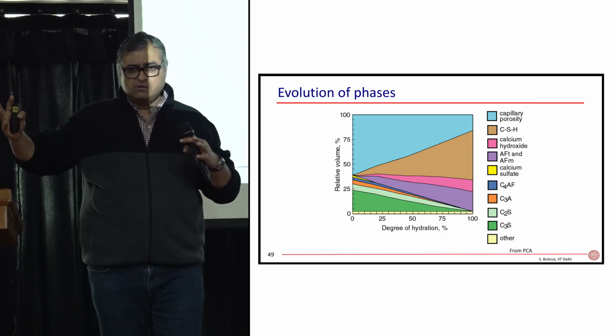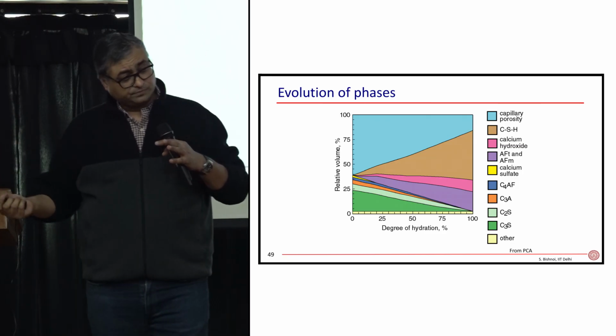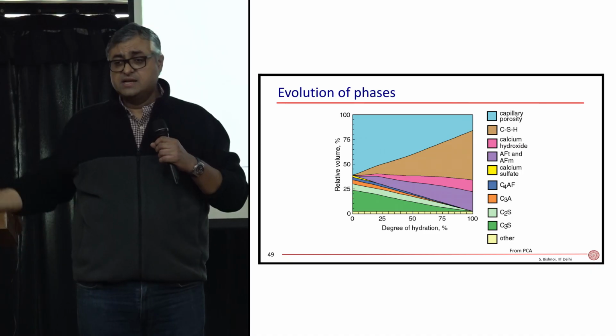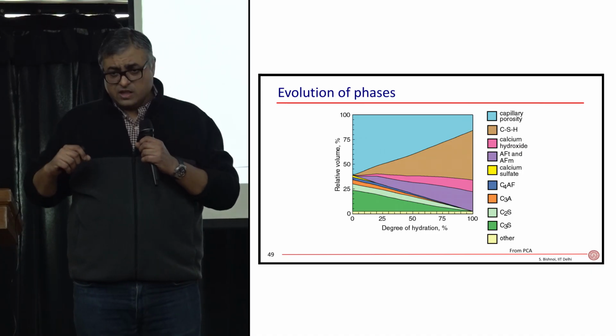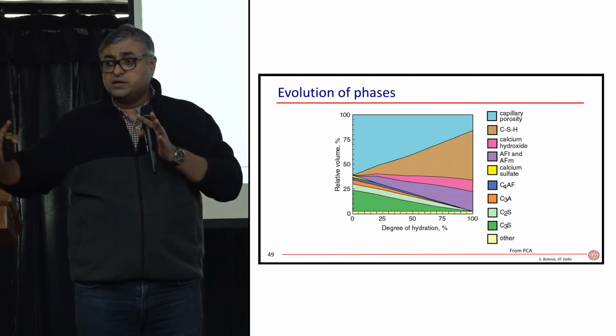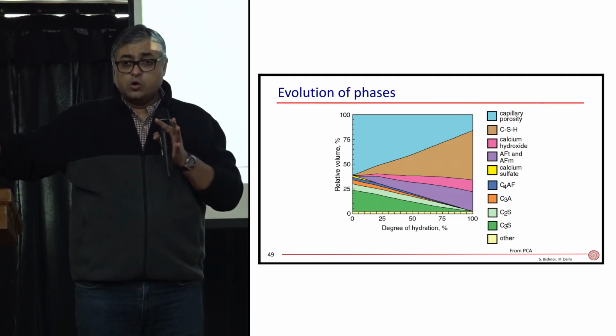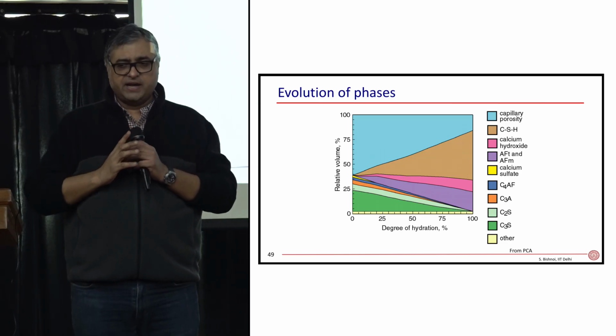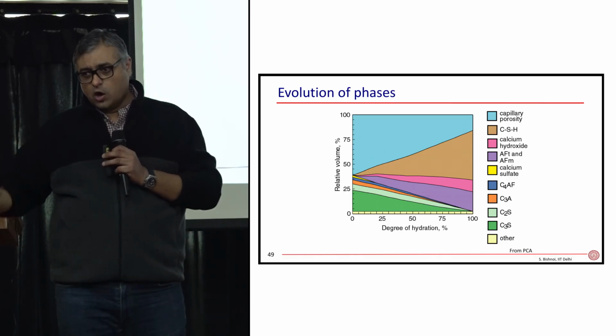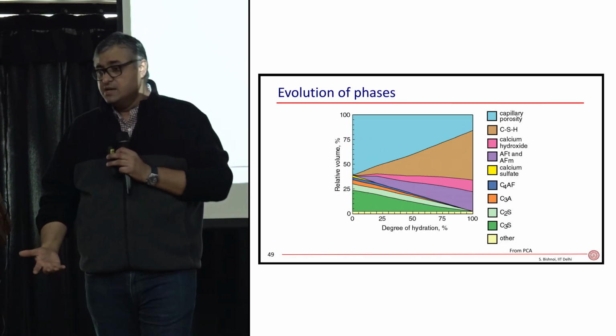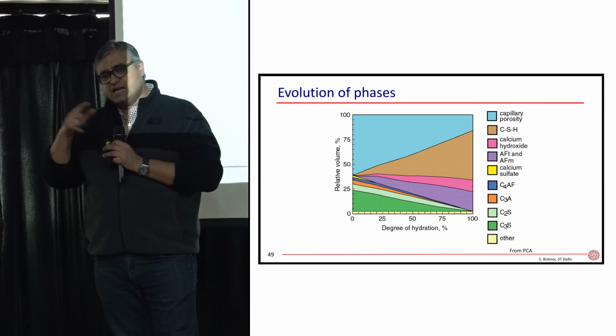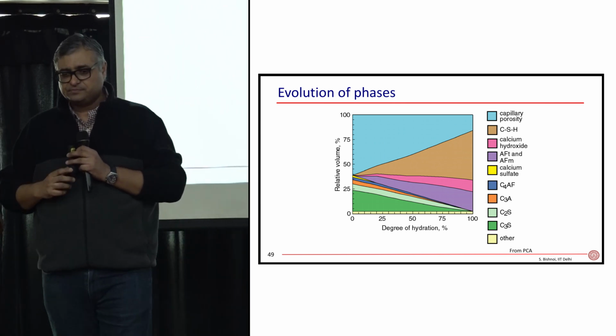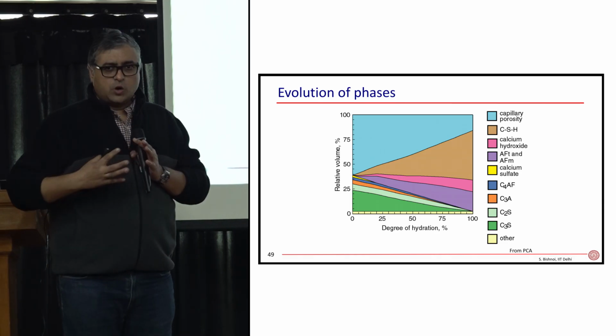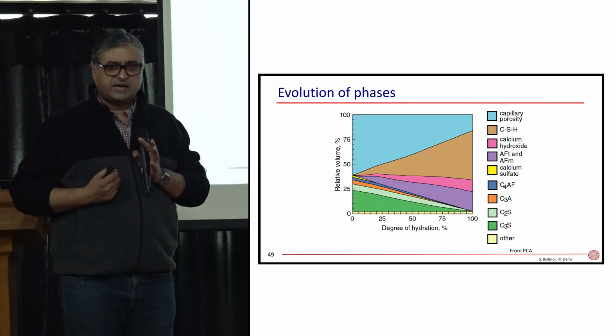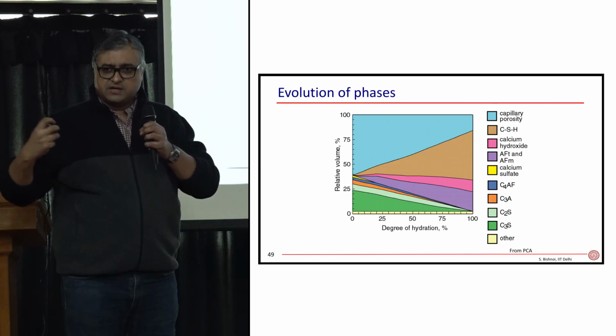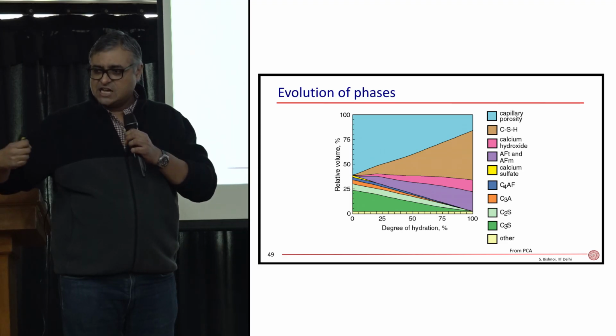Where is that volume coming from? Why is the volume increasing? The water. The water is getting incorporated into the solids. The water is giving you the solids, and the water is also contributing to the solid part. So the liquid that you added to the concrete at the beginning, which was water, to make the concrete workable so that you can give it whatever shape you want, that liquid is now becoming a solid and is now contributing to the properties of the concrete. The solid volume increases. I'll show you some numbers in a couple of slides. And because of that, these particles start to stick together because there is more solid and less liquid as hydration happens.